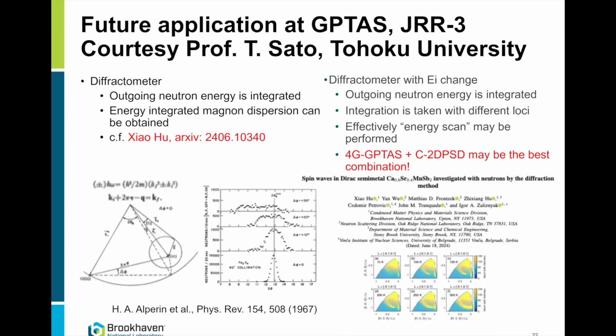When I showed these data about a year ago at a meeting where my friend Professor T. Sato from Tohoku University was present, he was excited. And I suggested that, in fact, a diffractometer measures at a given incident energy, but you can actually measure it at several different incident energies. And then you will basically have a spectroscopically resolved measurement on a diffractometer. This is an advance in our field because covering a large array of scattering angles with an energy analyzing machine, like a crystal analyzer, is very difficult. Or you can go to time of flight, and then on a reactor source, you have to chop your beam. But this method doesn't require that.